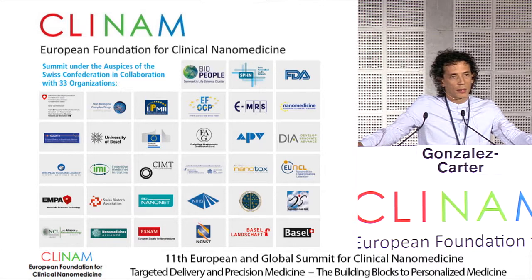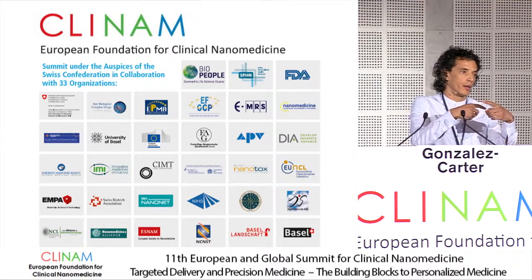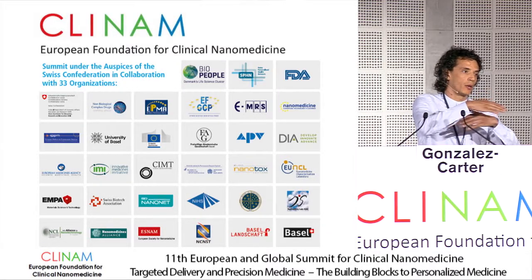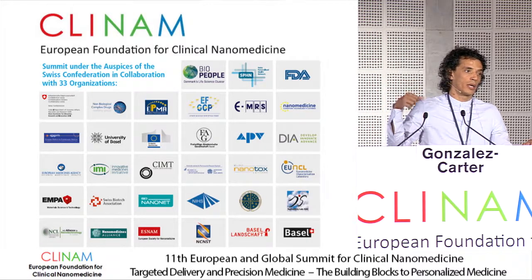Yeah, the CMC we have not fully, but we have overcome the limitation of it by cross-linking the micelles with EDC, so creating a peptide bond between the cation and anion monomer. So we see very little disruption of the micellar structure following internalization. And we have shown that the micelles are stable in high sodium chloride solutions.